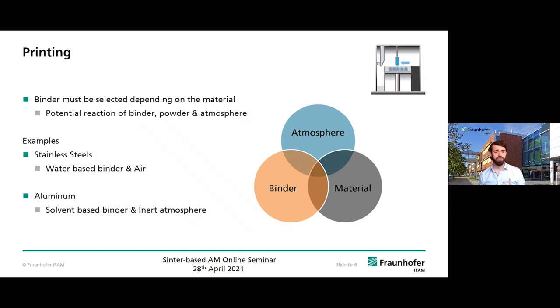One of the materials we are grateful for is stainless steel, as it's not corroded by water, and air is also not interacting with the material. So it's a really easy material for process development. Another one that is more crucial and not that easy is aluminum. As aluminum splits water into hydrogen and oxygen, you can't use water-based binders, so you have to switch to a solvent-based binder. And fine aluminum powder is also explosive, or can be explosive, so you should print it in an inert atmosphere. That's the first point, the printing process.